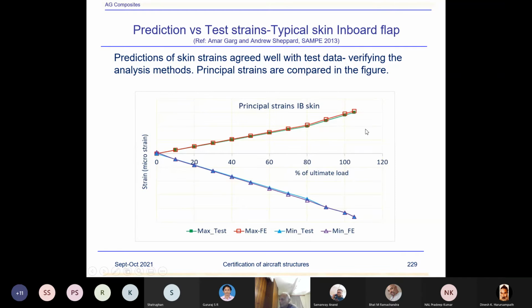So you would have, say, hundreds of gauges on a test component. You are testing at room temperature. You determine by test the strains and then verify that your analysis is also able to predict the strains. And as I explained to you, we had to match the predicted strains with the test data within plus minus 5%. And there was a lot of work done in order to refine the model, in order to generate the same strains. So that means you have got enough confidence in your analysis method. Okay, so once you have verified your analysis method, then you don't need to determine the test data in order to determine the final margins for the static or fatigue.